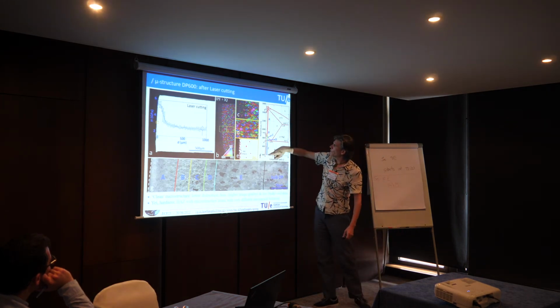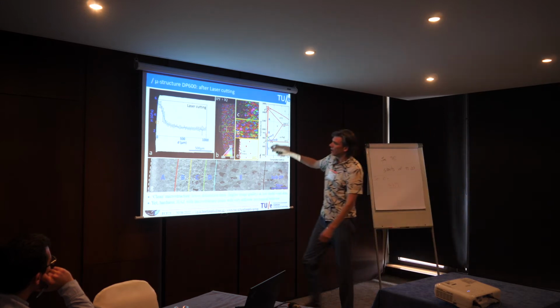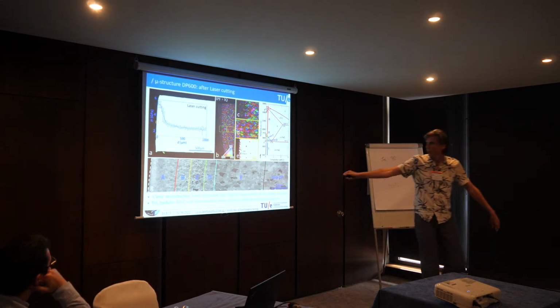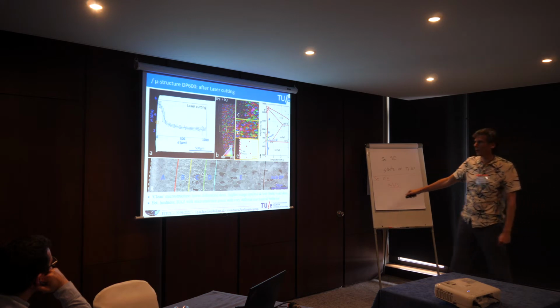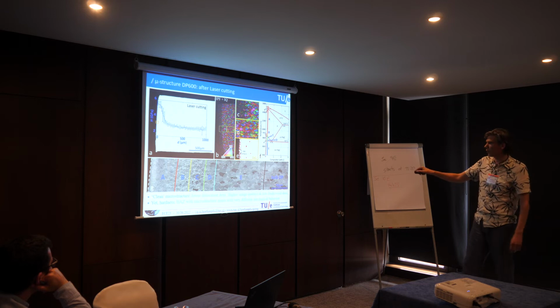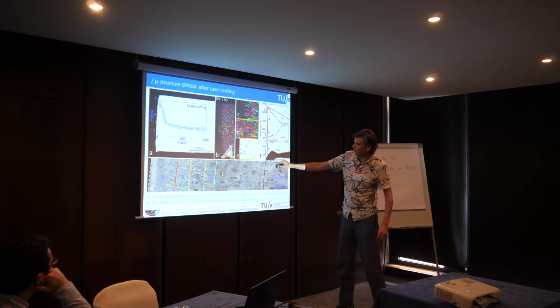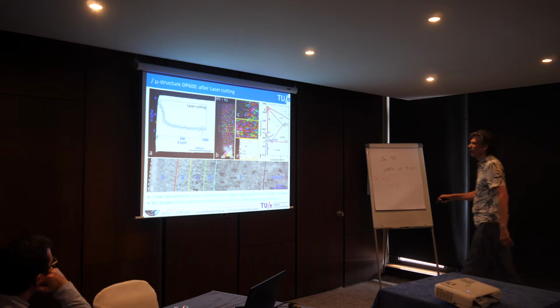So if you relate this to the thermodynamical phase diagram, you can see that here it went up to a high temperature and we get a rapid quenching, so we get full martensite. Here we get a more intercritical annealing range, so we can still have some full martensite in there, but only partial. And this is a regime that looks, in terms of microstructure, the same as the bulk, but this is a tempered region. We tested this, you can see that from the hardness.